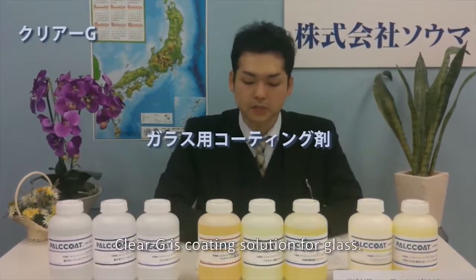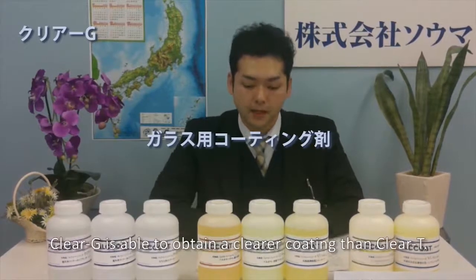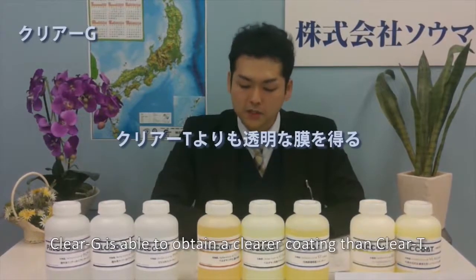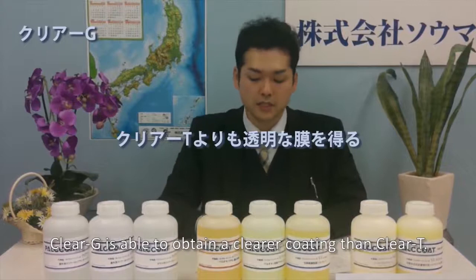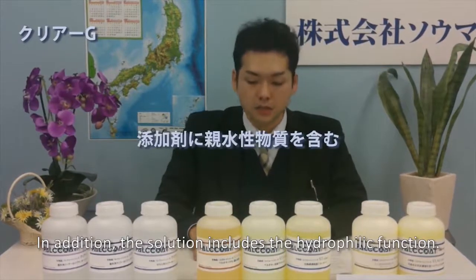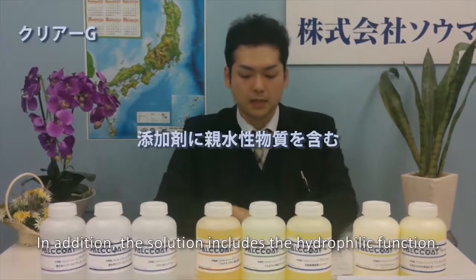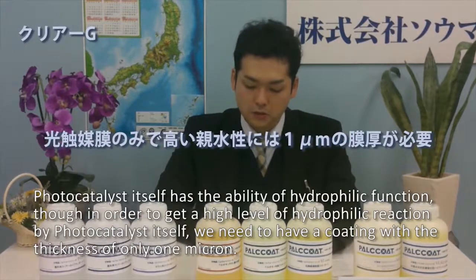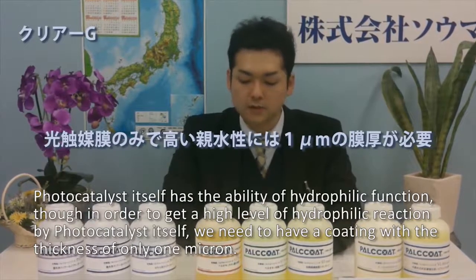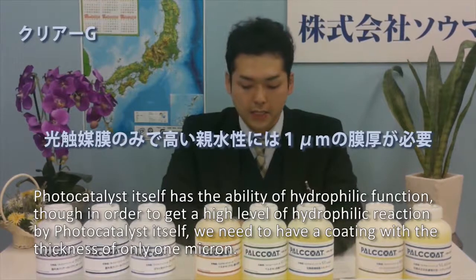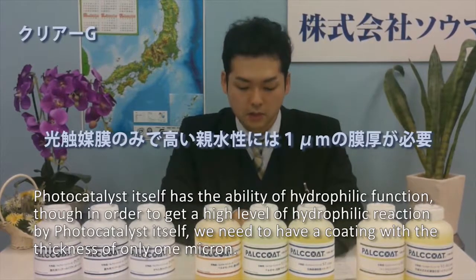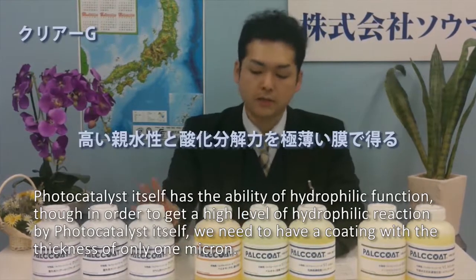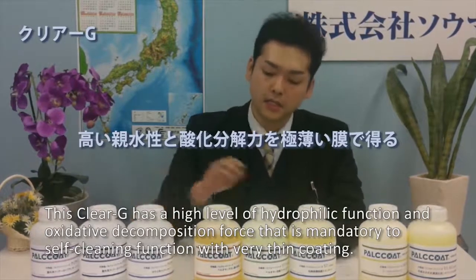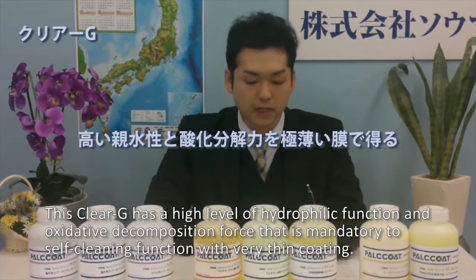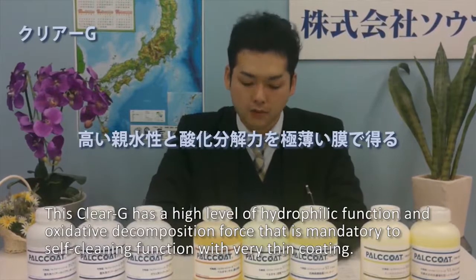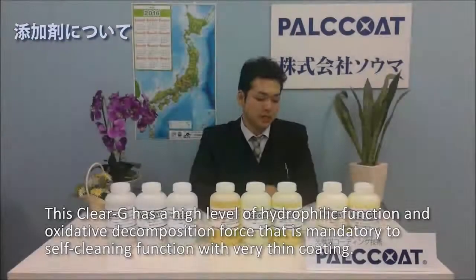Clear G is coating solution for glass. Clear G is able to obtain a clearer coating than clear T. In addition to solution, it includes the hydrophilic function. Photocatalyst itself has the ability of hydrophilic function, though in order to get a high level of hydrophilic reaction by photocatalyst itself, we need to have a coating with thickness of only 1 micron. This clear G has a high level of hydrophilic function and oxidative decomposition force that is mandatory to self-cleaning function with very thin coating.